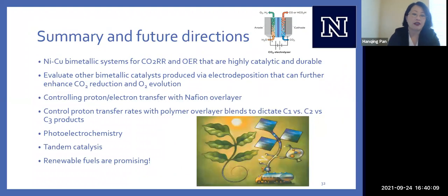And so with that, I'm going to finish up. We've looked at some bimetallic systems that are these bifunctional catalysts capable of catalyzing both CO2 reduction and oxygen evolution reaction, and they are pretty durable. I was able to demonstrate controlling proton and electron transfer rates with Nafion. We can also make these copolymer blends, and we can dictate 1 versus 2 versus 3 carbon products.